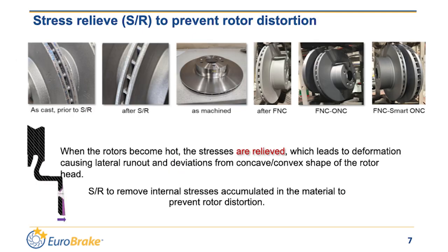Prior to FNC, it is mandatory to apply a stress relief process to remove all the internal residual stresses that can happen during machining and casting. The temperature of the stress relief should be set at 30 degrees above the FNC temperature. And after stress relief and FNC, the hardness and the shape of the rotor will remain stable.